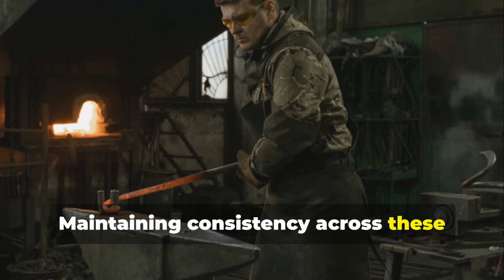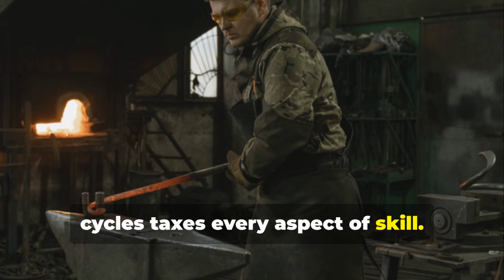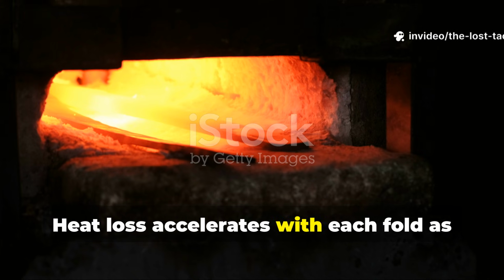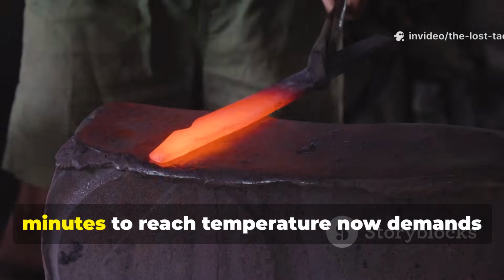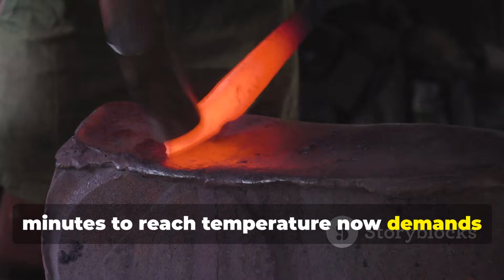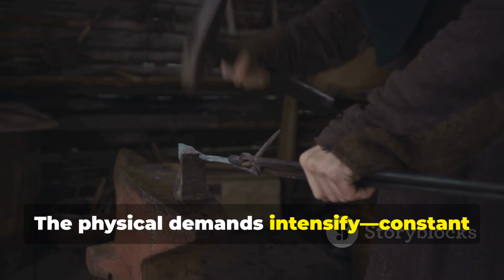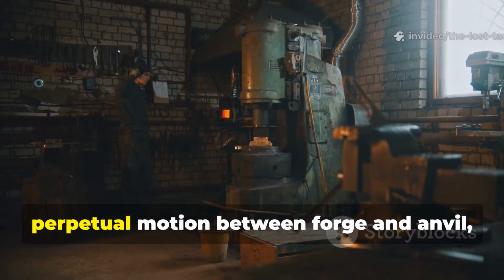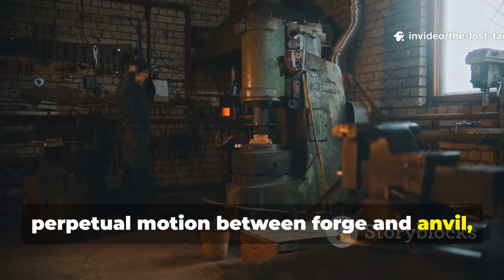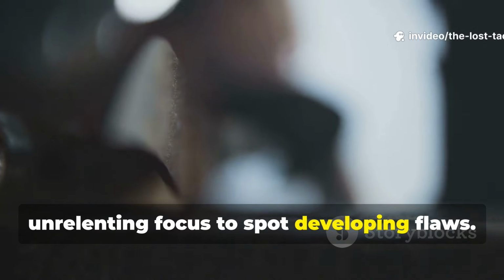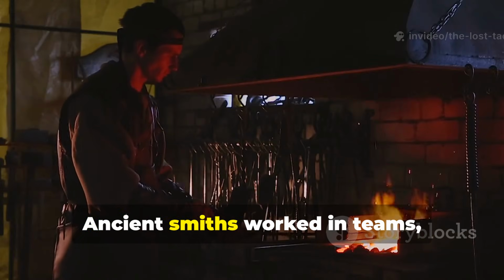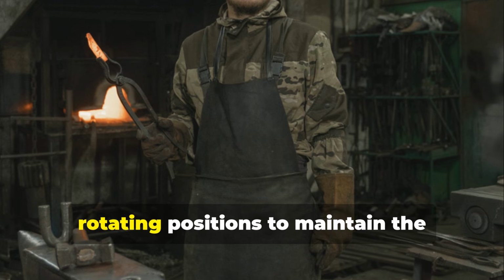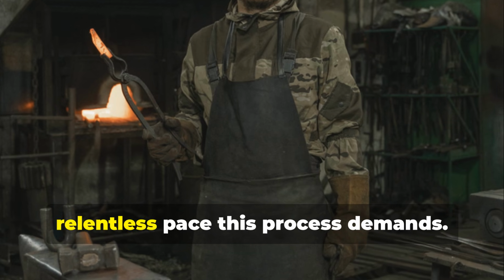Maintaining consistency across these cycles taxes every aspect of skill. Heat loss accelerates with each fold as surface area increases. What once required minutes to reach temperature now demands barely seconds of forge time. The physical demands intensify: constant hammerwork, perpetual motion between forge and anvil, unrelenting focus to spot developing flaws. Ancient smiths worked in teams, rotating positions to maintain the relentless pace this process demands.